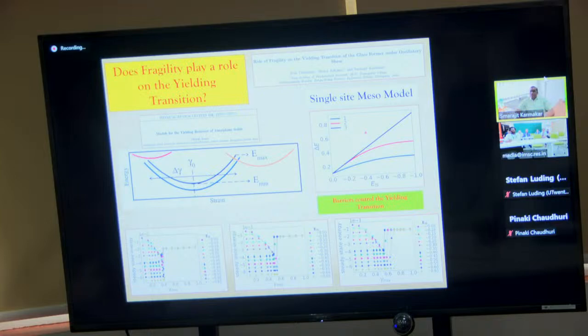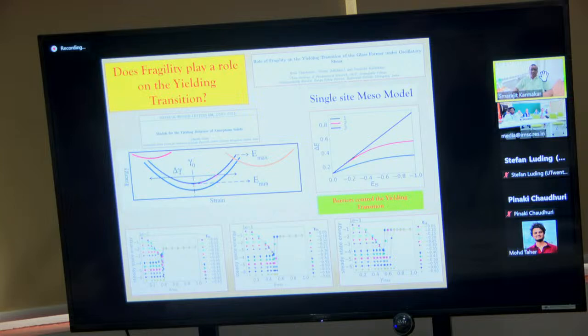But these observations can actually be explained if you do some sort of mean field calculation. This mean field modeling was first proposed by many people, and then subsequently Srikant proposed a new single site model for an amorphous solid and its yielding behavior. The idea is that you can think of the whole amorphous solid as moving in various energy landscapes. For example, at zero strain you are in this energy landscape, given by this black curve. As you strain the sample, the system goes up in this energy landscape and then topples to new energy minima, maybe this one. But if you do a reverse shear, then you can access this red minima. If you put in a few such rules, then more or less you can reproduce all this oscillatory shear diagram of an amorphous solid.